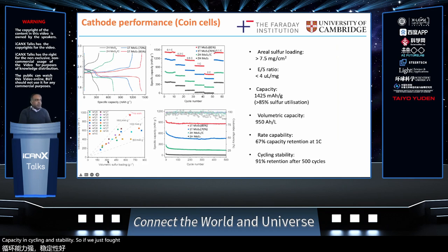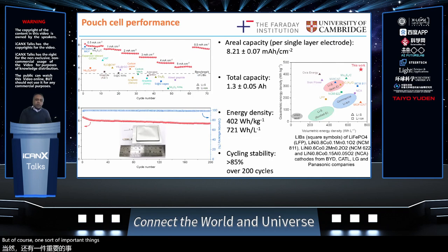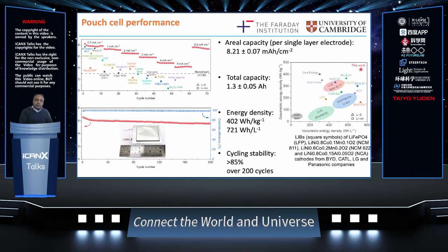If we plot the volumetric capacity versus the sulfur loading, our results compare reasonably favorably with what's been reported in the literature. But of course, one important thing to note is that the coin cell, as I said, uses conditions that are not really practical for a battery device. The conditions that we use for a coin cell are designed to give us an idea about how well the 1T MoS2 could potentially behave. But to really implement the 1T MoS2 in a practical cell, we have a dry room in Cambridge where we can assemble these pouch cells by hand.